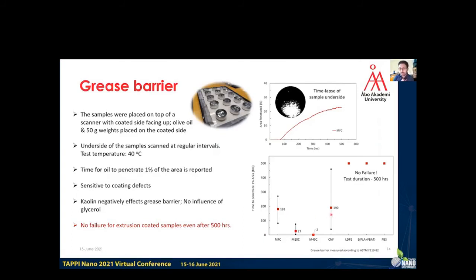MFC and CNF show very high variation and are sensitive to coating defects, just like oxygen barrier. It can vary anywhere between 50 hours all the way to 500 hours, where the test is actually terminated, and 500 hours is approximately 1 month. Addition of clay negatively affects the grease barrier, and glycerol addition did not have any influence. And when we have extrusion coated samples, there was no failure even after 500 hours. And that was the duration of the test.